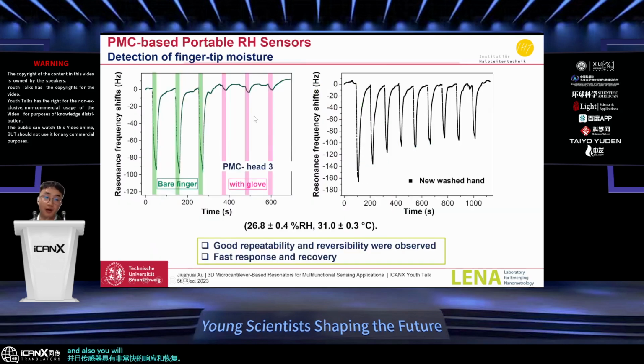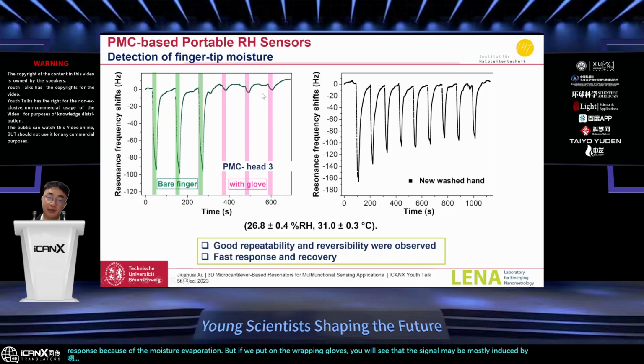And also you will find it interesting that we are actually evaporating moisture, or humidity, all the time to the environment. If we measure our finger, you can see a clear response because of the moisture evaporation. But if we put on a wrapping glove, you will see that the signal, maybe mostly induced by heating, by temperature, is very small.